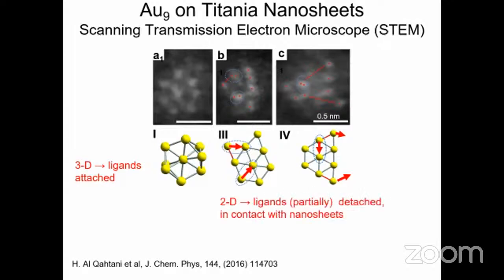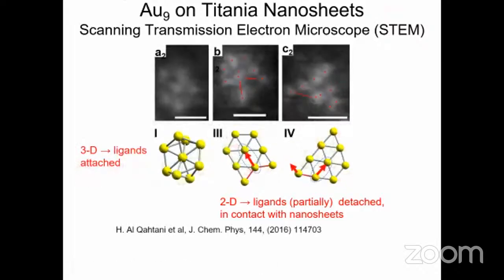The first category, as you saw here, what you're seeing now is that the white spot is just the single atom itself. And the scale bar here is 0.5 nanometer, which is related to the gold core of our nanocluster. And we saw them in 3D at the beginning. Then when it is removing some of the ligands because of the attachment to the nanosheet and because of the electron beam, we saw a two-dimensional structure of this nanocluster. This will help us understand the structure and how our gold nine cluster looks when it's deposited on the nanosheet.